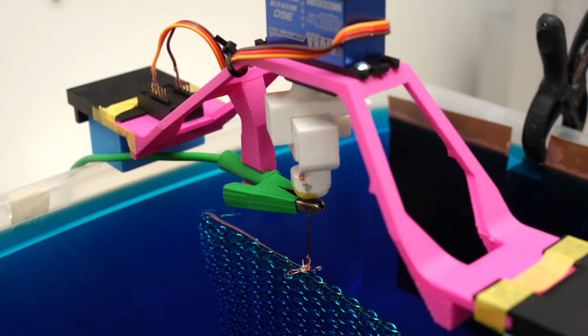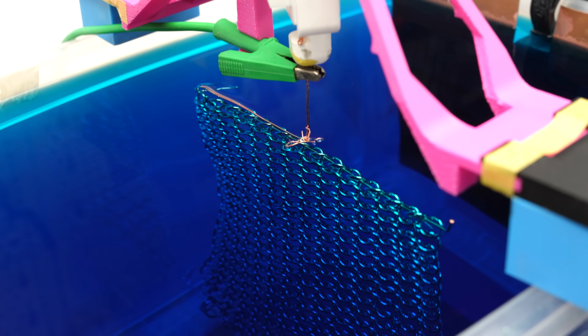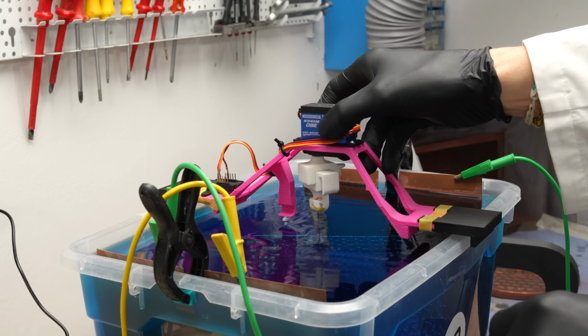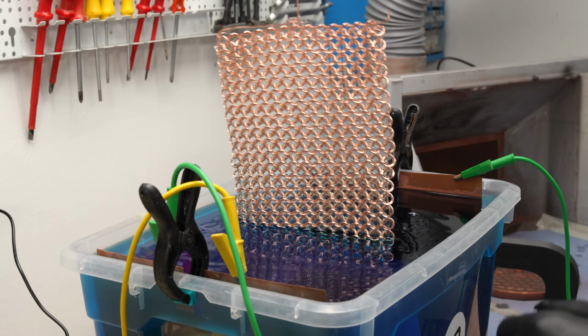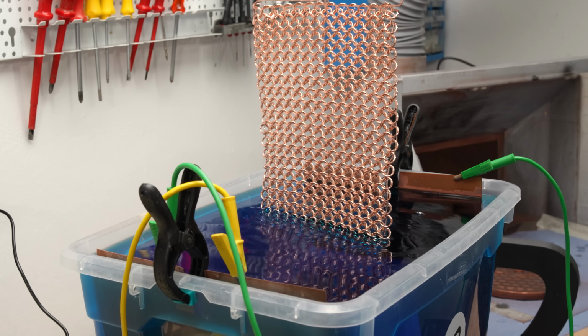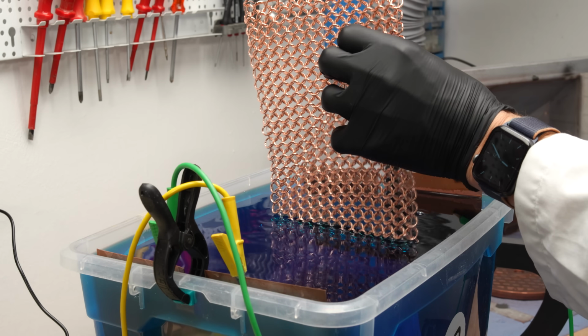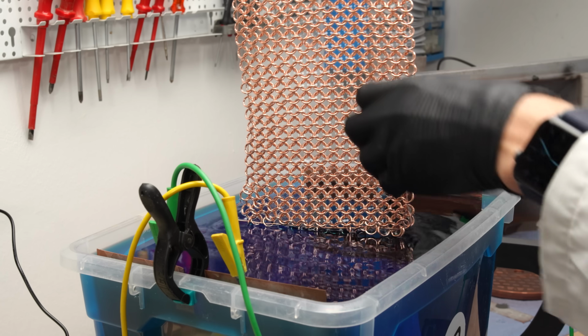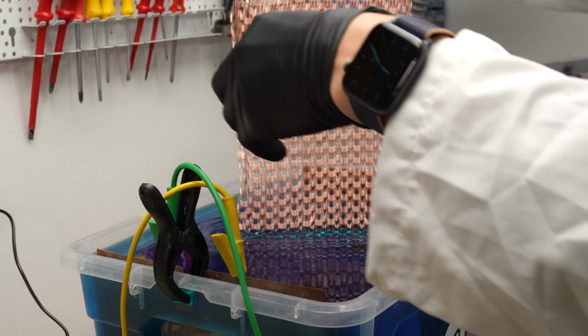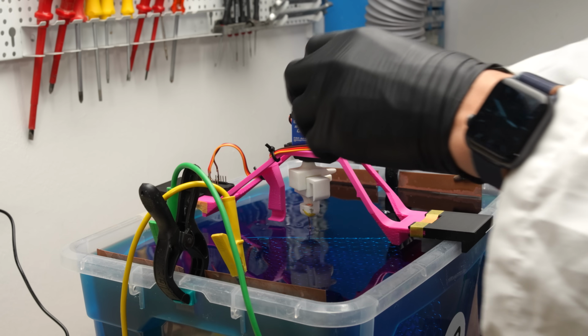This time I'm not using the rotation function because the moving print would get too close to the anodes. So you'd think everything would get plated together after a short time, but nope, not really. I took it out 3 times and moved it around a bit to loosen up some of the connections between the segments. Then I figured it would be smart to turn on the stirrer. Yeah, that backfired. The deposits on the anodes broke loose and messed up the whole bath.